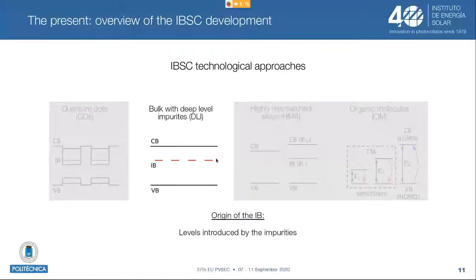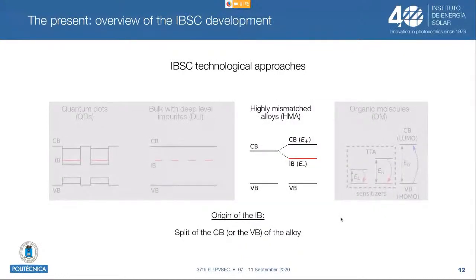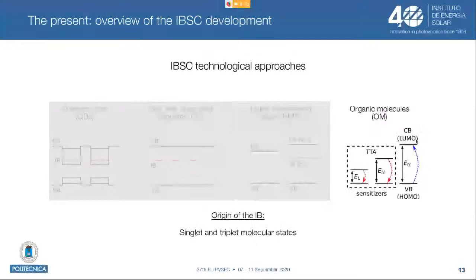A third approach is to use highly mismatched alloys. These materials are a special kind of alloy in which the inclusion of a small element causes the split of one of the bands into two. So we get, as plotted here, a band in the middle that we would call the intermediate band. And finally, it was proposed to use organic molecules in which the singlet and triplet molecular states play the role of the intermediate band. By combining low band gap molecules that we call sensitizers, via the process of triplet annihilation, we can create an electron-hole pair in the large band gap absorber. So these are the four approaches.